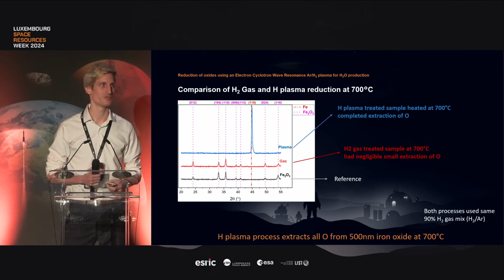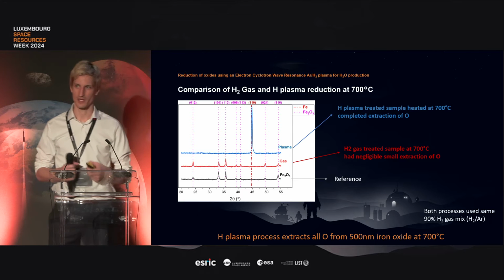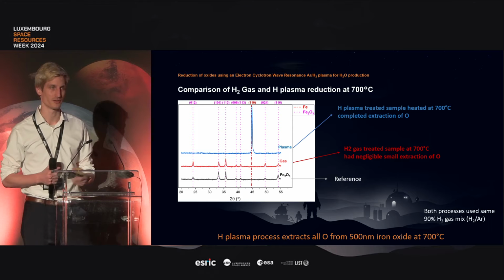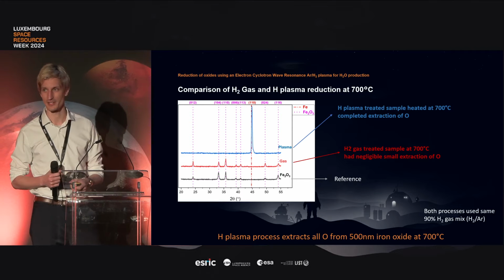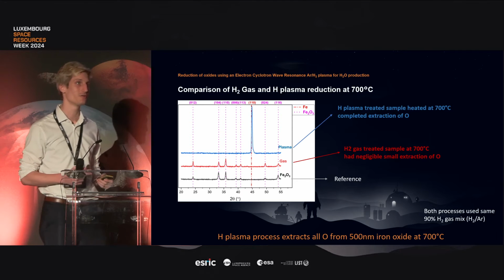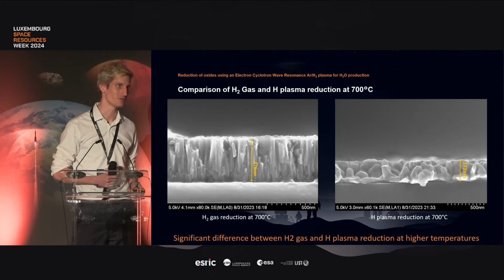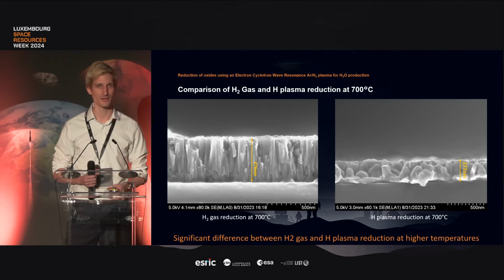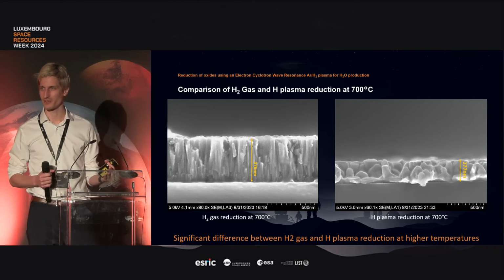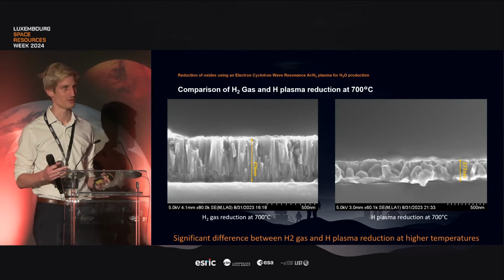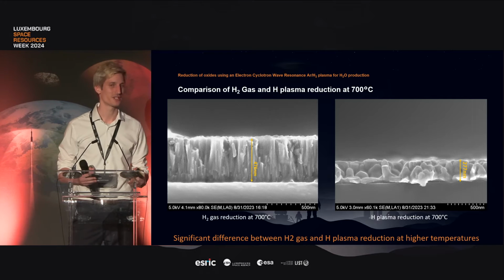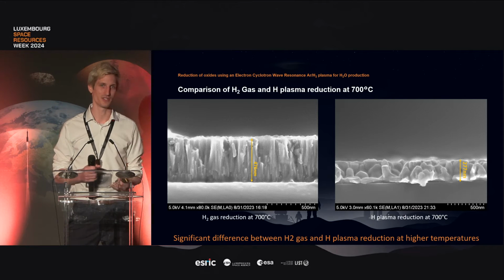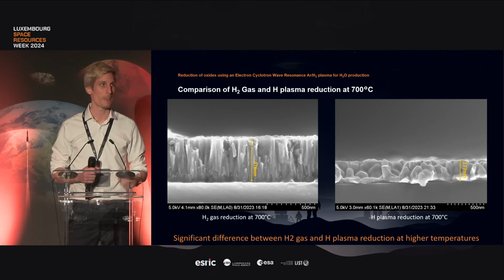Since we looked through all of the material with the XRD measurements that we performed here, we concluded that we extracted almost all of the oxygen from 0.5 micron of the iron oxide material at 700 degrees. But let's go away from the graphs and see how it looks more visually to confirm it. On the left side, scenario with the hydrogen gas reduction, and on the right we have the plasma reduction where the material is treated at 700 degrees.